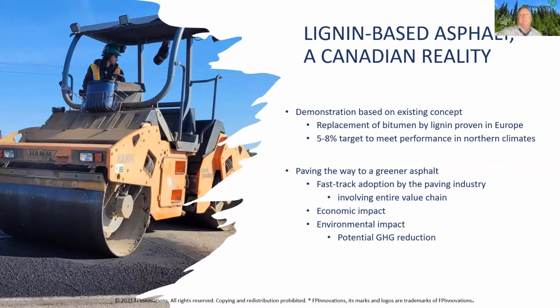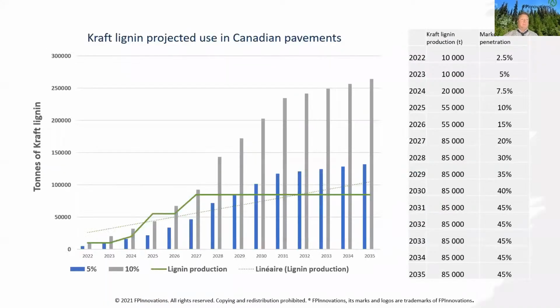From the learnings of the demonstrations, we will be able to conduct full life cycle analysis on the economic and environmental side. Lignin use in the Canadian pavement is projected to increase in the future for two reasons. First, paving is anticipated to increase at 3% per year. And second, because we expect increasing market penetration as lignin asphalt becomes more accepted and sought after. The chart shows projected demand if the lignin is incorporated at 5 and 10% of bitumen replacement in the asphalt.